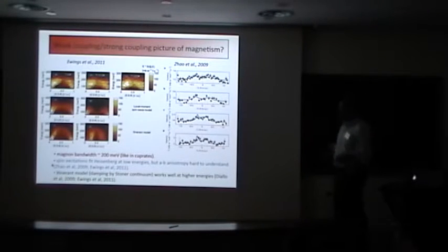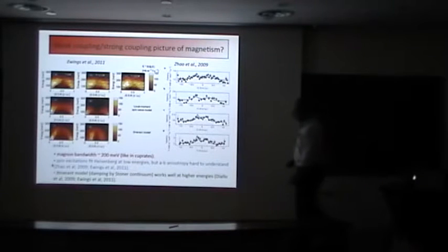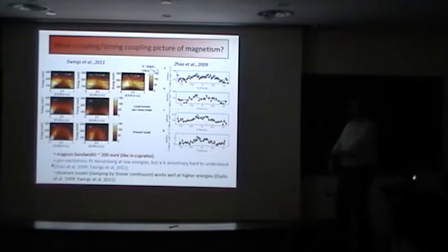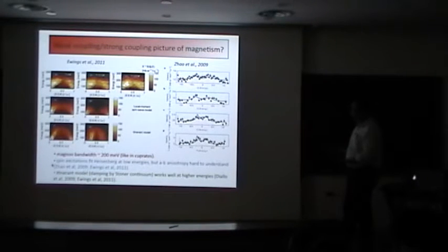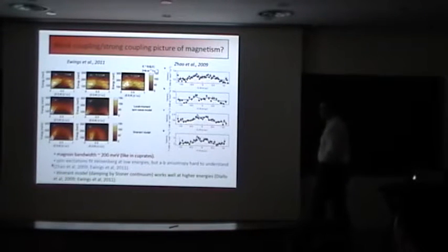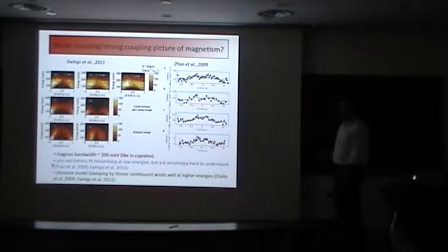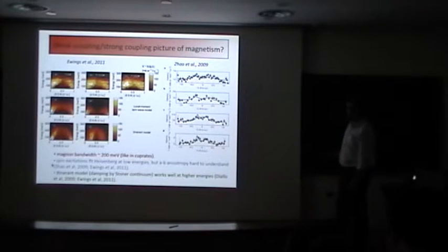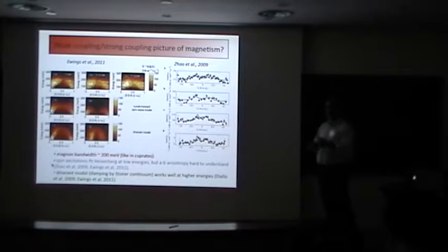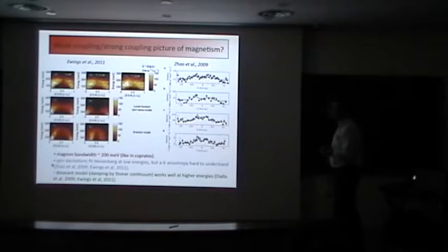That gives a J, in a single Heisenberg-like model, on the order of what it is in the cuprates. If you try to fit the spectrum to a Heisenberg-like model at low or high energies, you find you can give a very good fit for the dispersions shown on the previous slides. But the a-b anisotropy means it has to be very different along one direction compared to the other.